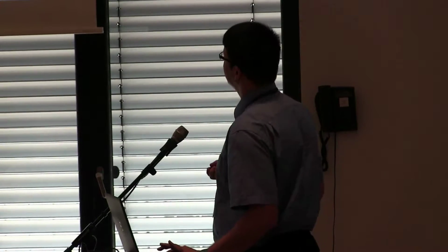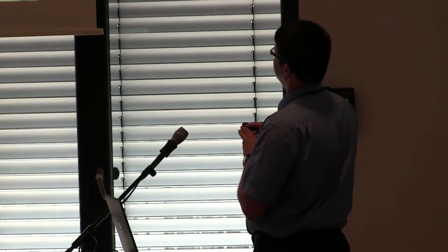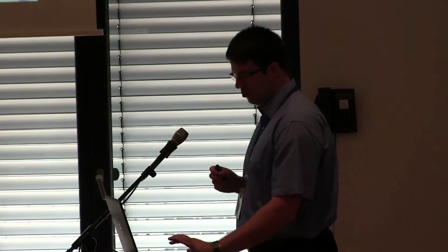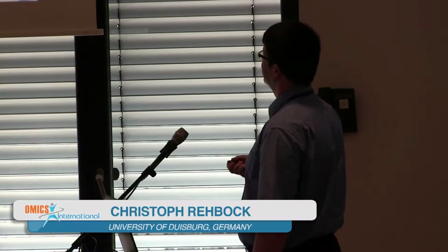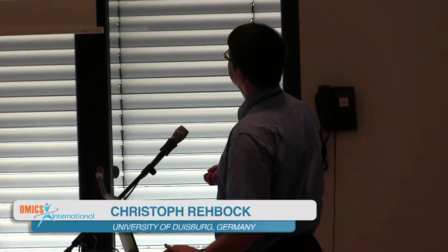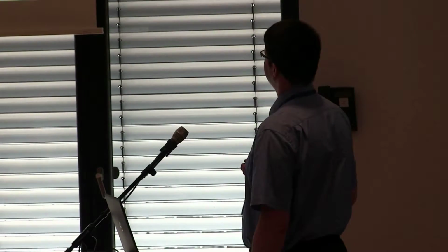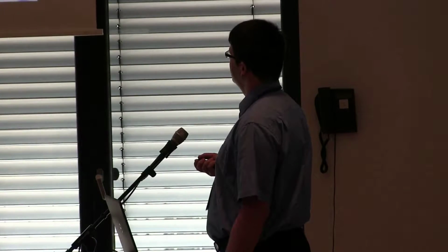However, when we increase the ionic strength a bit, when we are, for example, in this regime, then we have a larger amount of ions. So they can stabilize a larger surface area, which leads to an earlier stopping of the particle growth, which then leads to smaller particles. So I could show you in this first part that to obtain ligand-free colloidal particles, we can use pulse laser ablation in liquids, and we can control our size by salts using soft ions and micromolar salinities.